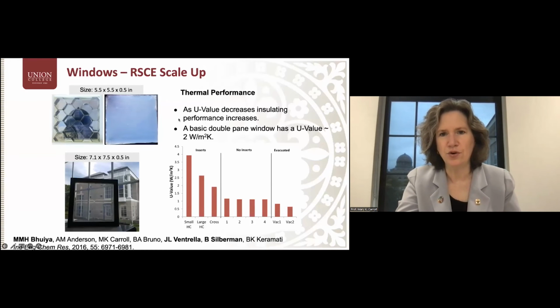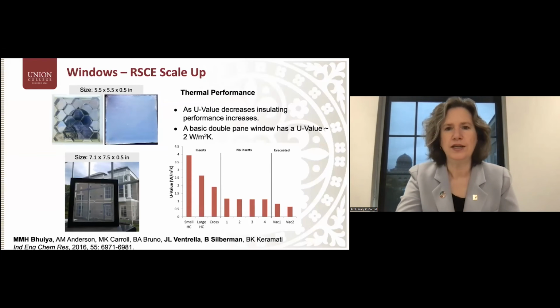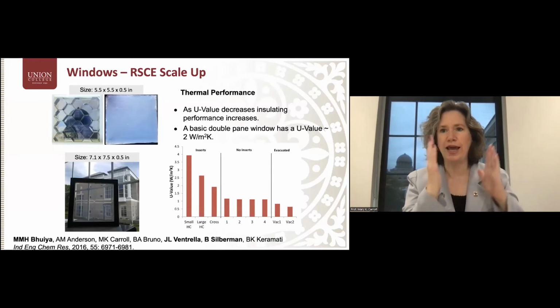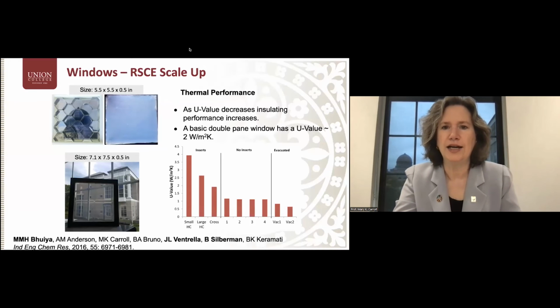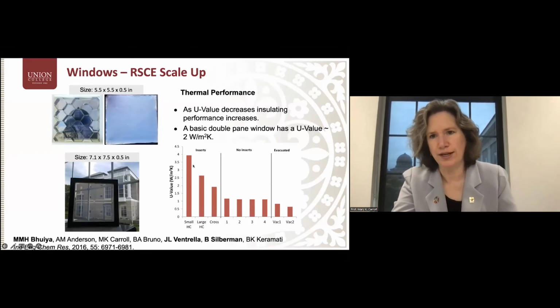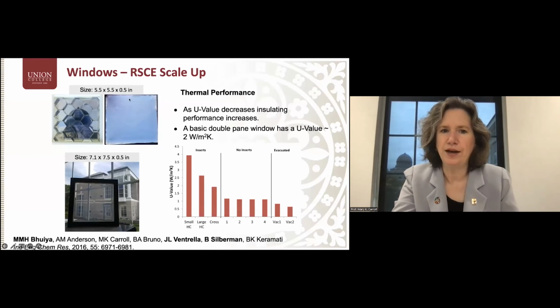And so just to orient everyone, as the U value decreases, insulating performance increases. And a basic double pane window with air in the center has a U value of about 2. And so with the metal inserts, of course, we were getting thermal bridging, so that is not very impressive. But just putting a piece of monolithic aerogel about 12 millimeters thick in between the pieces of glass drops the U value by almost a factor of 2.